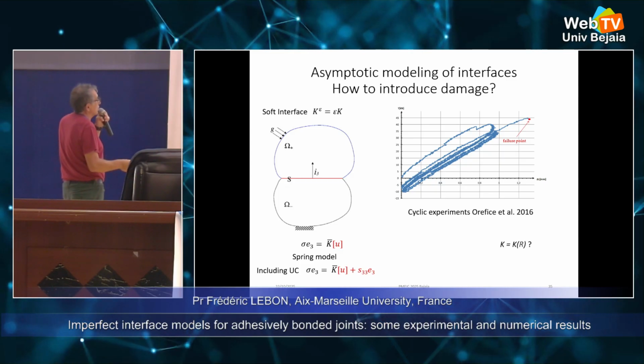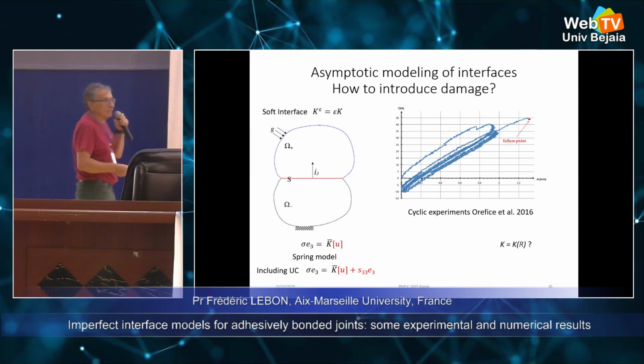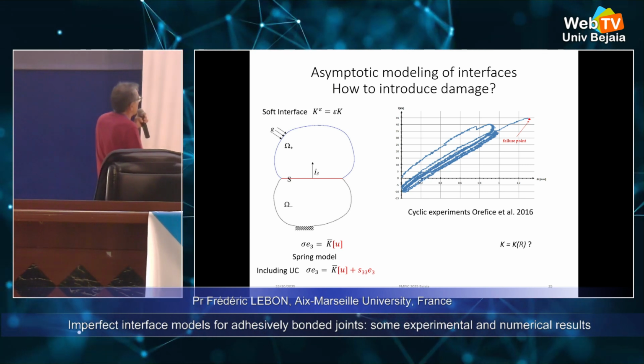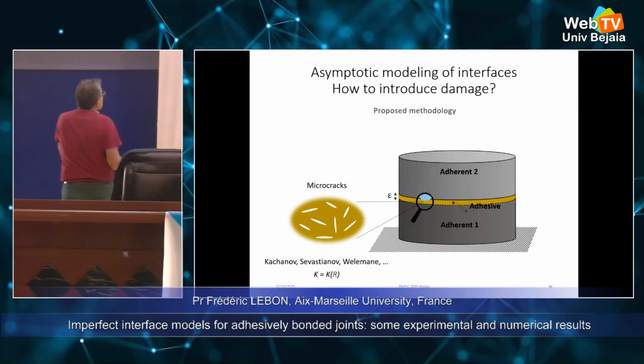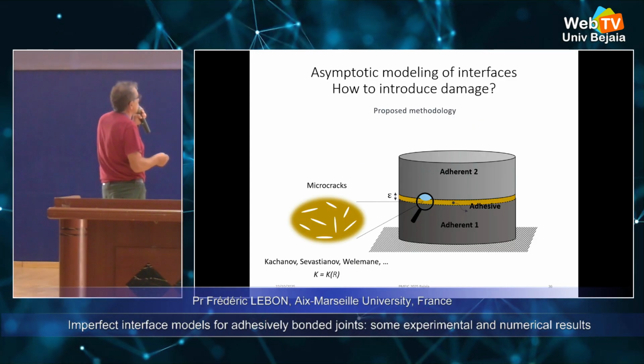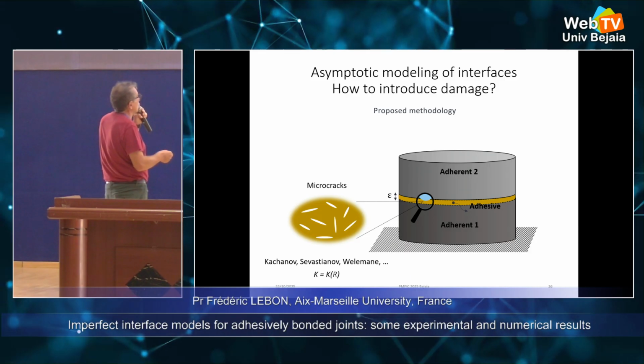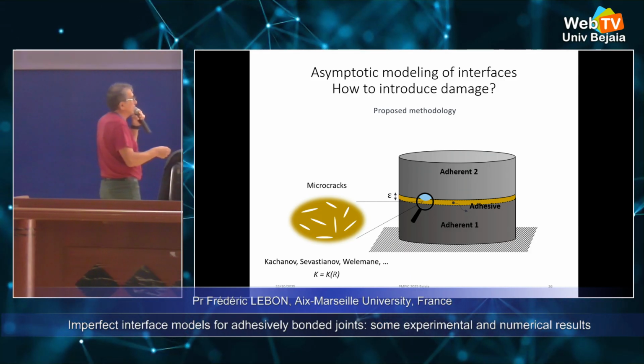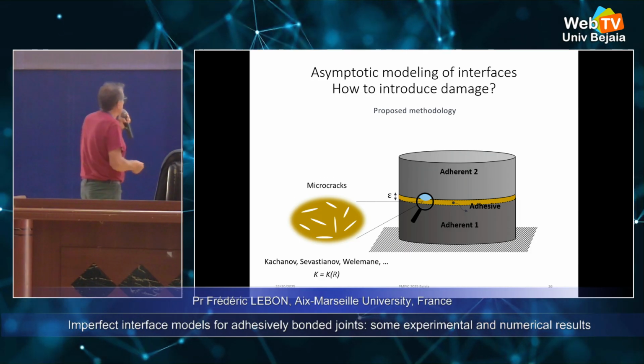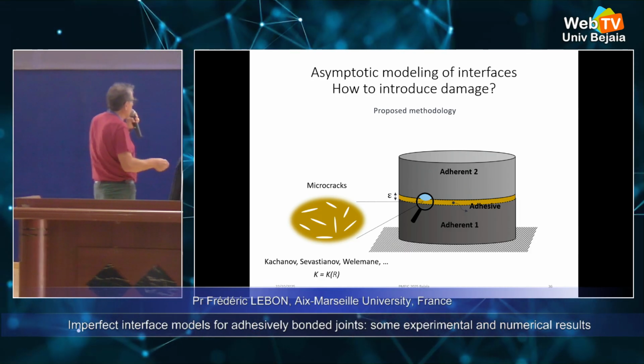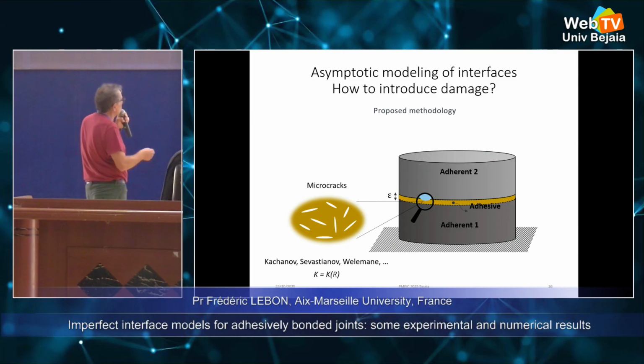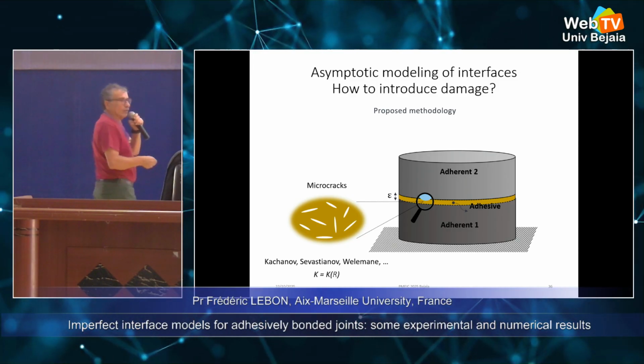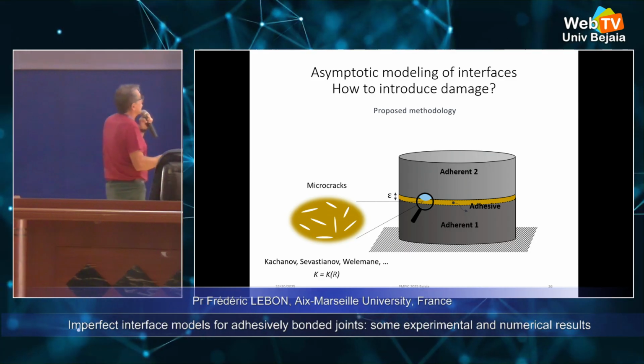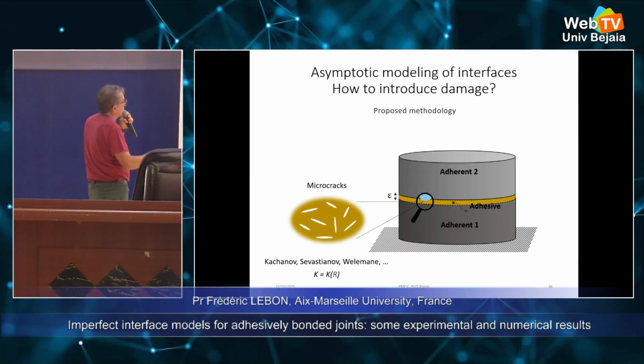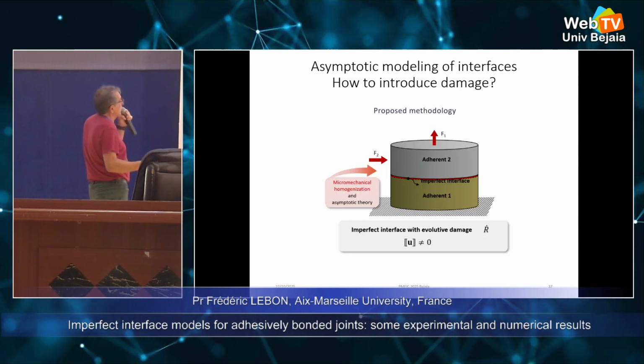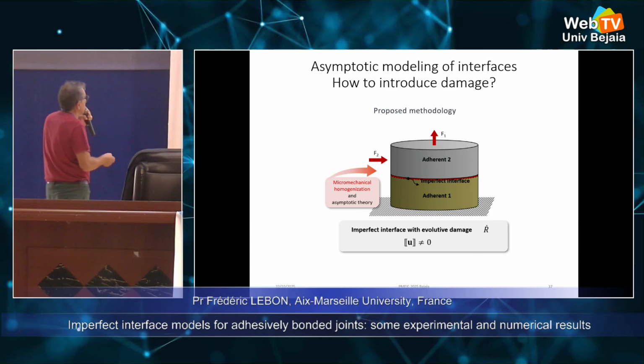So there is damage in the material. So the idea is that there is a damage parameter, and the stiffness of the spring depends on the damage parameter. Okay. And to do that, an idea is to introduce micro cracks in the glue using homogenization. For example, there is a long bibliography on how to introduce micro cracks in materials in order to obtain homogenized materials. We use this kind of materials, and after that we can proceed using asymptotic expansion.